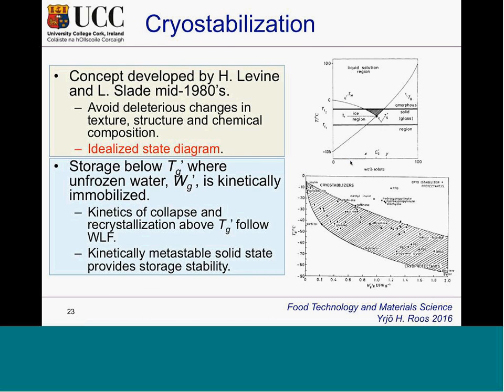This also relates to the cryostabilization concept that was presented by Harry Levine and Louise Slade in the 1980s with a state diagram and a lot of material showing how the different sugars, carbohydrates, organic solutes behave with water at low temperatures. And there was the T sub G prime, which did not really agree with what we call nowadays the T sub G prime, because that was more on the melting side, but there was a relationship established with that parameter and the kinetics above the transition, showing that physical-chemical changes like crystallization and reaction kinetics are related to the glass transition.